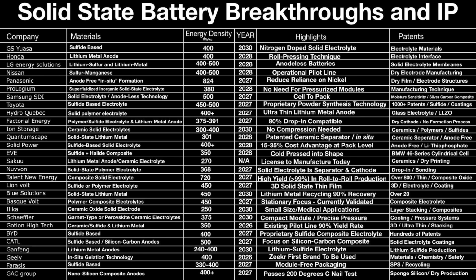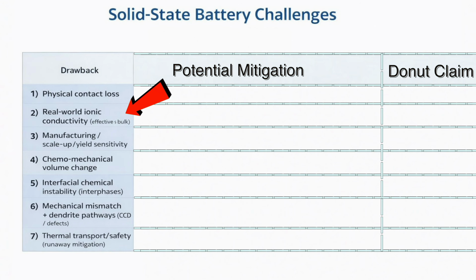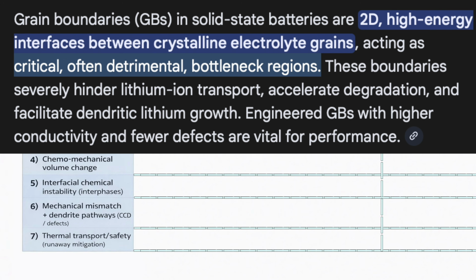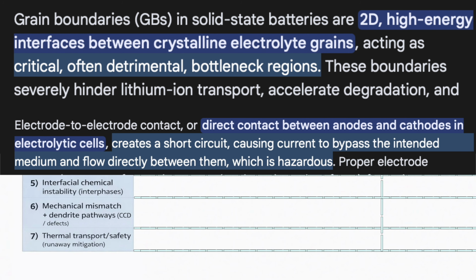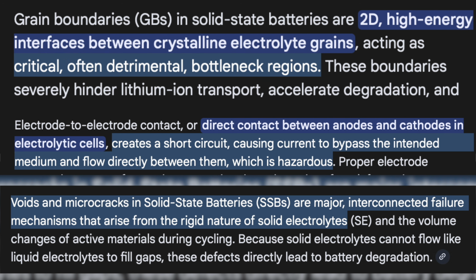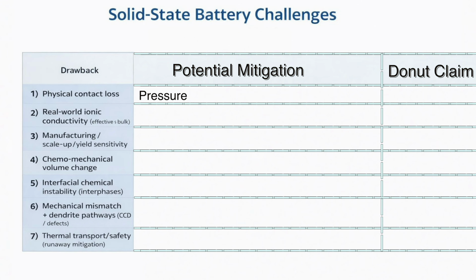But that chart is pretty dense and might be hard to look at, so we can simplify it a little bit. Physical contact loss, real-world ionic conductivity, manufacturing, chemomechanical volume change, interfacial chemical instability, mechanical mismatch, and thermal issues. So how do you solve each of those? The physical contact problem. Examples include grain boundaries, electrode to electrode contact, and voids and microcracks. Is typically mitigated with pressure. That's the best mitigation so far, albeit an incomplete one.